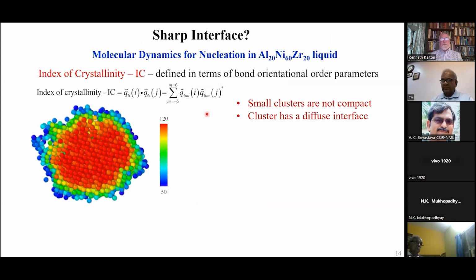Let's take the first question of a sharp interface. These are some molecular dynamics for nucleation in an aluminum nickel zirconium liquid. And what has been defined here is what's called an index of crystallinity. It's defined in terms of bond orientational order parameters, if you want to see the equation. But what it means is it's an order parameter. It has one value, a high value, if it's in an ordered crystal, and it has a much lower value if it's in the liquid. And shown here is a range of values. 120 would characterize the center of this nucleating cluster, where you can see the order pretty evidently with your eyes. This is a highly ordered part of the cluster. 50 is what it has in the liquid, which is shown around here.